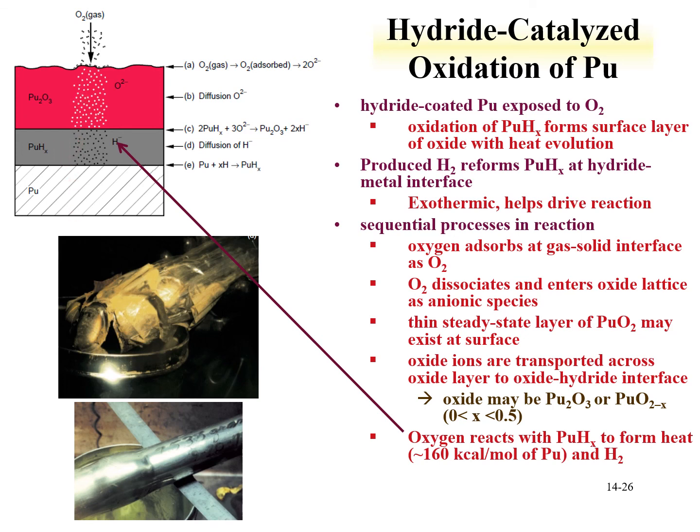Now, why this is important is that for storage of plutonium metal, you want to prevent any sort of oxidation from occurring, because it goes from a very dense material to a lighter material. That means you have swelling, as shown here in an example of 2 storage containers that contain plutonium metal. Upon the oxidation reaction, the material converted from the metal to the oxide and the hydride, swelling the package, and in one case, bursting the package.